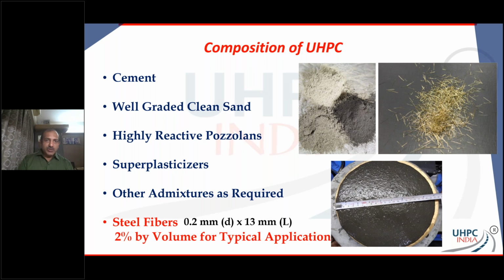So I've been talking about UHPC for the past 5 minutes, but here is a picture that you want to see. UHPC is mainly just about powder, right? You're not going to have any 10 mm aggregates or 6 mm, 8 mm aggregates or anything thereabout, right? You are going to mostly have sand in it, and that too extremely fine sand. All other, highly reactive pozzolans and, nice cement and a good superplasticizer, etc.